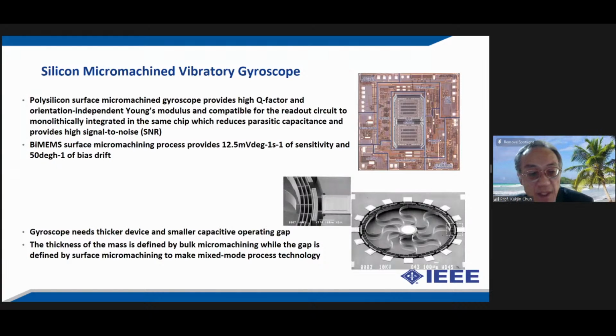So it provides a very small capacitive operating gap, and the thickness of the mass is defined by the bulk micromachining, but the gap is defined by the surface micromachining, meaning that you grow the oxide between those two, and then remove the oxide, and that will give you the gap of those two moving parts. So it's called a submicron gap gyro. Okay.